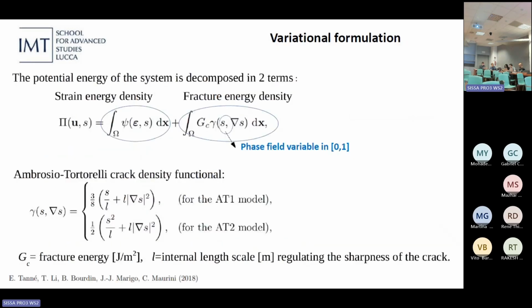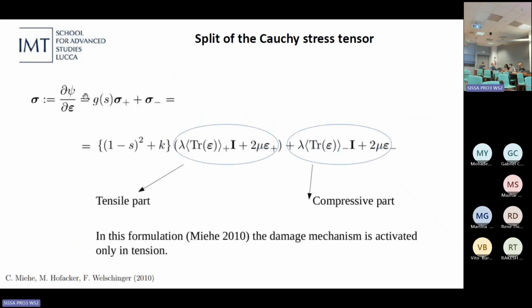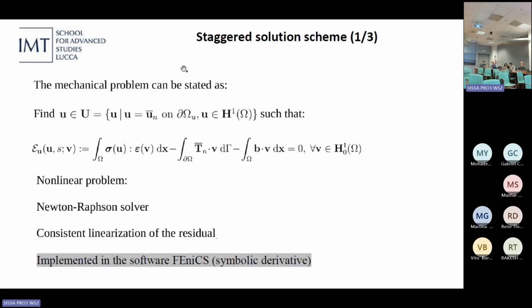Okay. What about the Cauchy stress tensor? We have that the damage function here is associated to the tensile part of the Cauchy stress tensor, and we can see here that these plus and minus involving the strains are basically the spectral decomposition of the strain. So that's the reason why this model is called spectral model. And we can see that in this model, the damage mechanism is activated by internal stress states of tensile kind, basically.